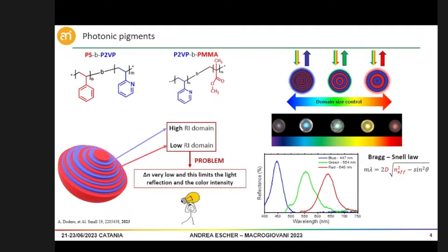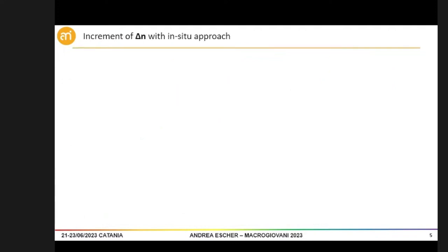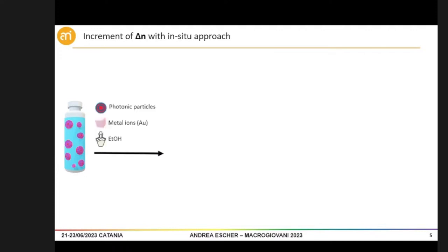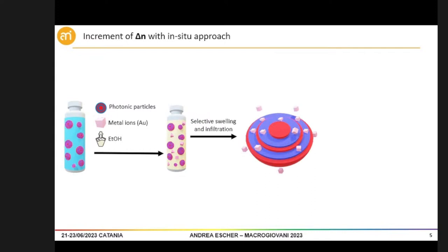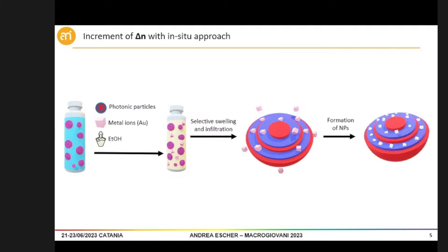I approach this problem with two different methodologies. The first one is called the increment of the dielectric contrast by in situ approach. The idea is to start with a water emulsion of photonic pigments, change the solvent from water to ethanol, and thanks to that we can promote the selective swelling of one of the two polymer domains, and also promote the infiltration of metal ions from the solution. In this case, I use gold metal ions. I finally have the formation of nanoparticles inside the pigments by thermal treatment or chemical reduction.